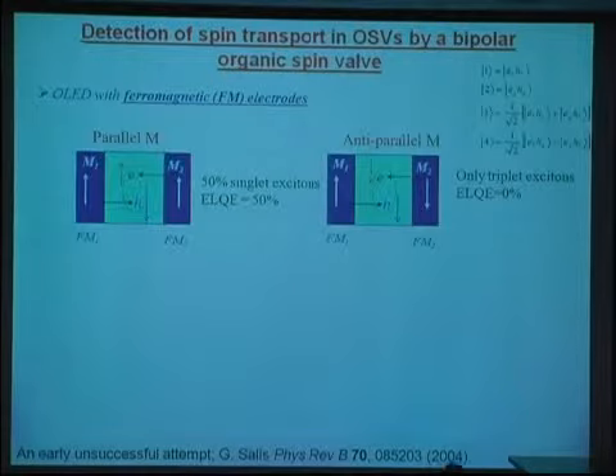Okay, so I would like to give you the second proof that we actually have spin transport in organic spin valves. In this configuration, I use bipolar organic spin valves. What does bipolar mean? I use one ferromagnetic electrode for hole injection, and the other one is for the electron injection. So if you have magnetization in this direction, and you inject the hole into the material, you inject the electron in the opposite direction. This is a very important issue that I would like to emphasize.